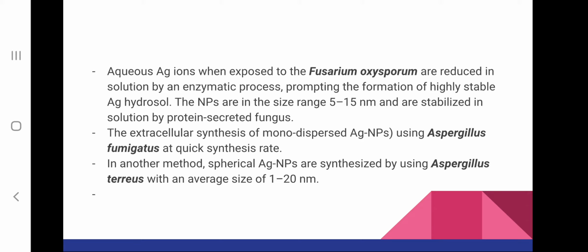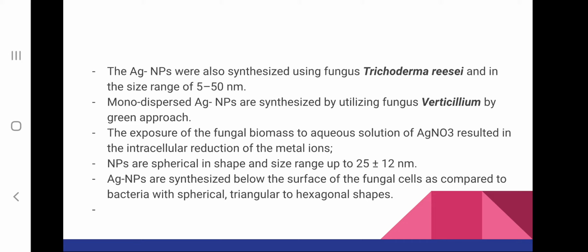Then extracellularly nanoparticles can be synthesized using Aspergillus fumigatus, and Aspergillus terreus can synthesize spherical nanoparticles of 1 to 20 nanometer size. Then Trichoderma reesei can synthesize nanoparticles of 5 to 50 nanometer, and Verticillium can synthesize monodispersed silver nanoparticles.